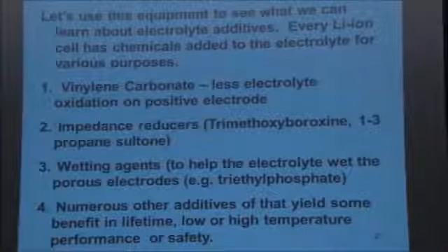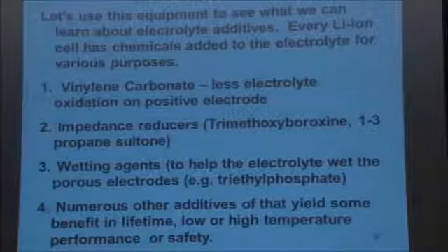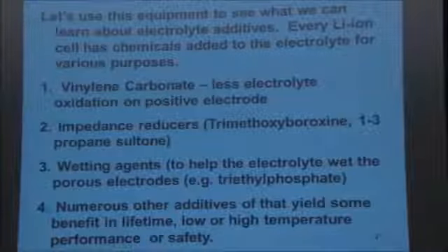People add additives that reduce the impedance of cells and limit gassing in cells. They add wetting agents because they're trying to feed them through the manufacturing process as fast as possible. You add the electrolyte to the cell, it has to fill into these porous electrodes. So if you add a wetting agent, it does that quicker, but how does it impact the cell lifetime? And all kinds of other things. Typical lithium-ion cell might have 5 additives in it for various purposes.